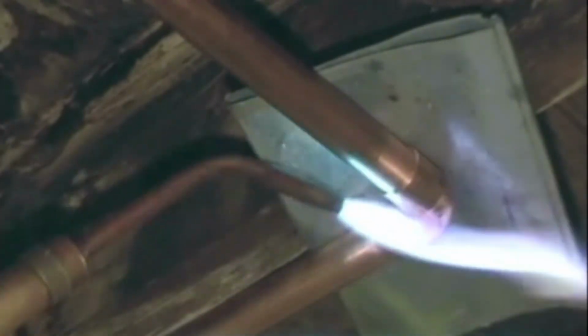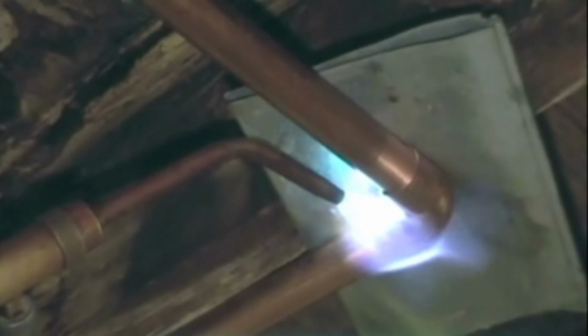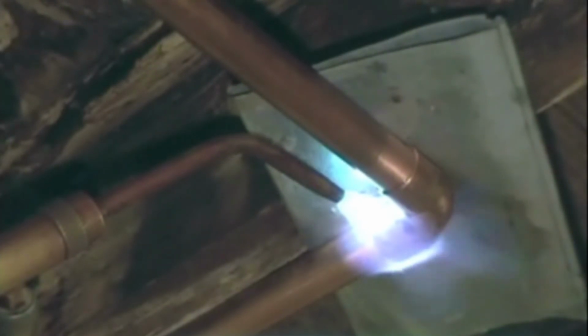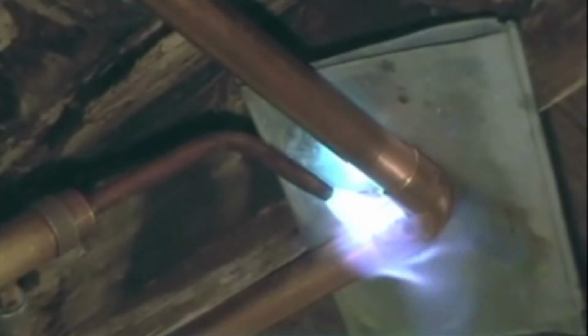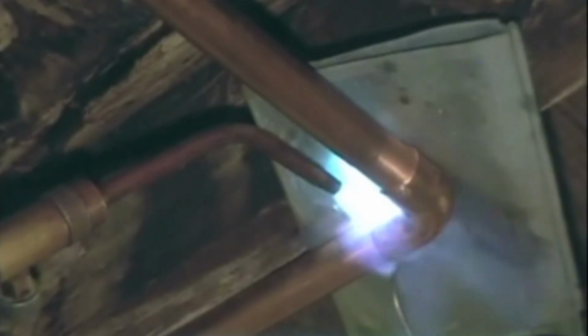95/5 signifies an alloy of roughly 95% tin and 5% antimony. Okay. This alloy behaves very, very differently under a flame than the old leaded solder. In what way? Leaded solder had a very wide plastic range, meaning there was a large temperature window where it was in a mushy, workable state before turning completely liquid or completely solid. So it's incredibly forgiving for beginners. Extremely. Yeah. But 95 tin antimony solder has a much higher liquidus temperature and a very narrow plastic range. So it goes from solid to liquid fast. It transitions from solid wire to watery liquid almost instantly, meaning you have to be vastly more precise with your heat.